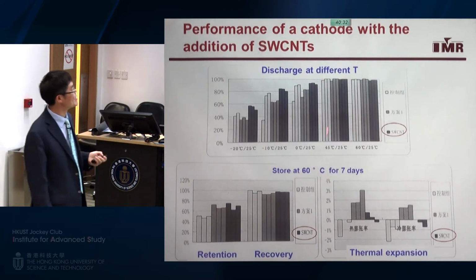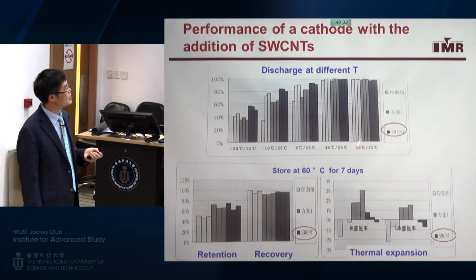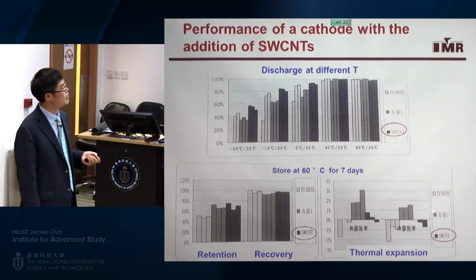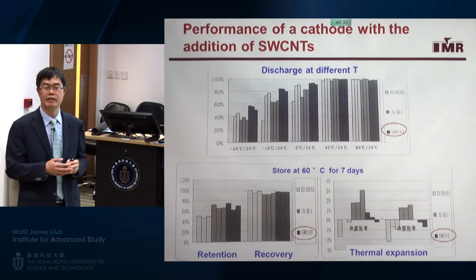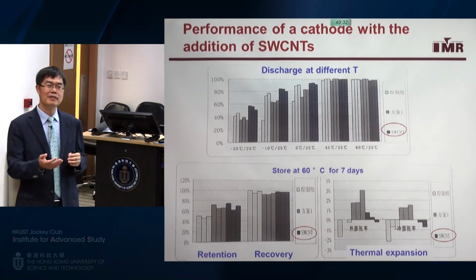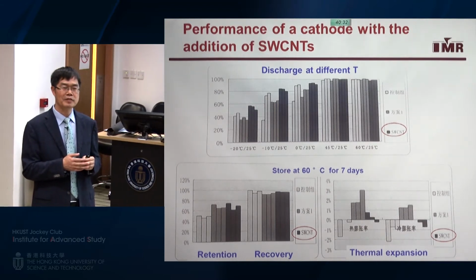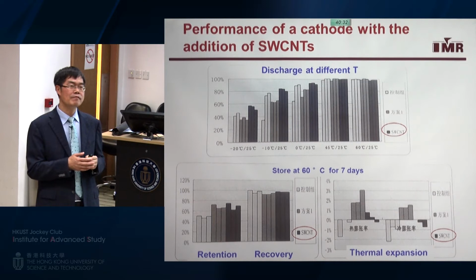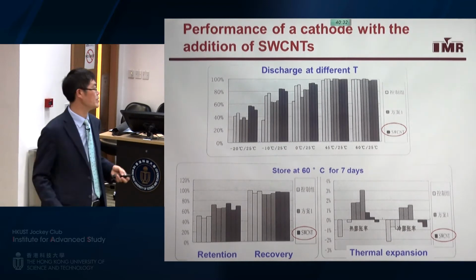And more importantly, you can see here the discharge at different temperatures, and storage at 60 degrees C for 7 days. With the aid of single wall nanotubes, the thermal expansion is very small compared to other additives. That means safety is better at high temperature. As we know, Samsung had a big problem because of the safety of a battery. So if we have a very safe battery, of course, it's very important for portable electronics and electric vehicles.